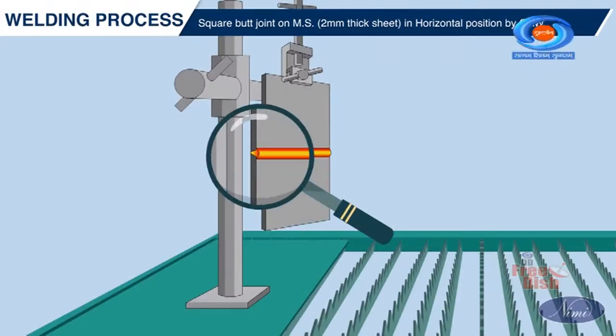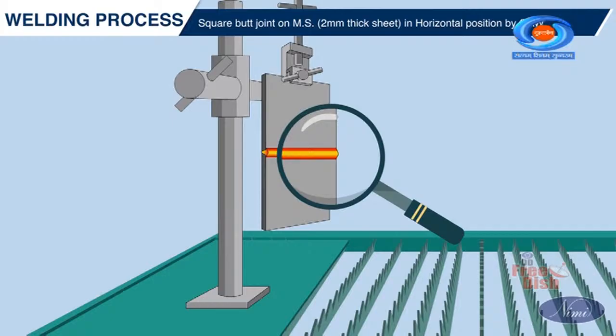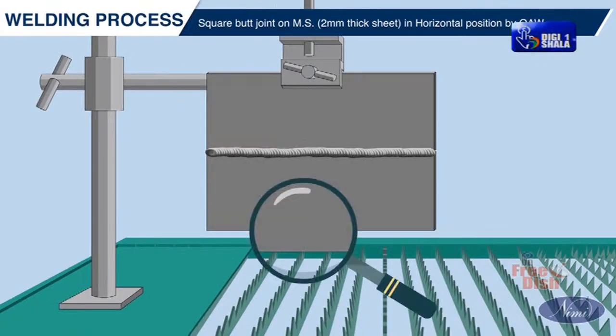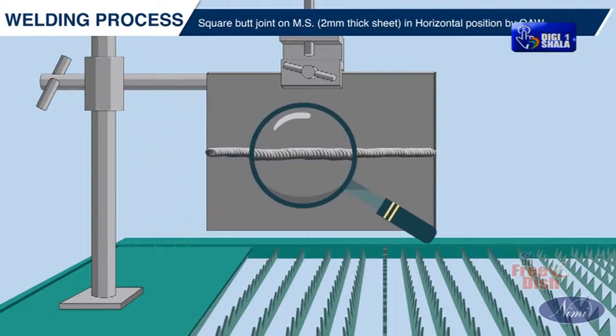Ensure both edges melt equally and up to the root of the joint. Check the weldment for the correct profile with complete penetration.